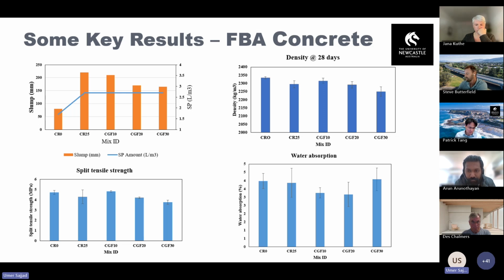So what we found is that if we increase the amount of superplasticizer and slightly increase the amount of water in the concrete mix to account for the water absorption of furnace bottom ash, we can have a better mix which is workable and can be easily placed. So that's why the initial slump of these FBA concrete mixes is slightly higher compared to control concrete. Then if we come to the density, we have measured the density at 28 days. It is the hardened density. So we can see that as per density, the furnace bottom ash mixes lie within the range of the normal concrete densities. And there is not much difference between control concrete and the mixes with furnace bottom ash.